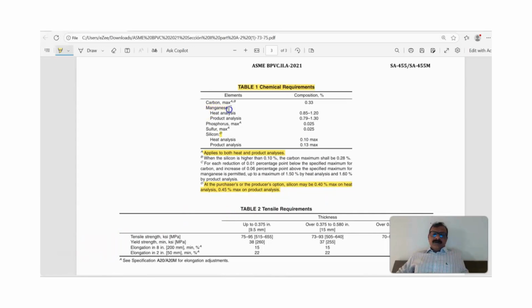Then manganese, very important, heat analysis it is 0.85 to 1.2 and product analysis 0.79 to 1.3%. But there is a note here, C. So the note C says for carbon reduction of 0.01%, increase maximum to 0.06%. Then manganese is permitted up to 1.5% by heat and 1.6% by product analysis. So this 1.2 and 1.3% of manganese will become 1.5 and 1.6.